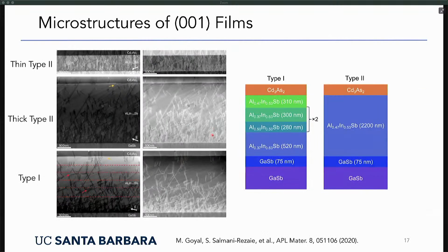Here's an example of microstructures, in particular for the 001 films. What's shown here in the cross sections are different buffer layers, and their lattice match to cadmium arsenide, which I mentioned is difficult for 3-5. And you can see why it's difficult. You can see these grown on gallium antimonide substrates are very heavily dislocated. As you grow very thick buffers, the dislocation densities are reduced by dislocation reactions. But the good news is that the cadmium arsenide contains significantly fewer dislocations than the 3-5 buffer layers, and that has something to do with the large unit cell. Cadmium arsenide has a very large Burgers vector, and it keeps these dislocations from going into the cadmium arsenide films. Nevertheless, what you do to the buffer layer matters.